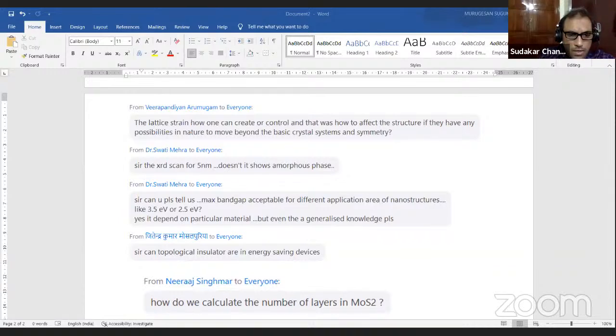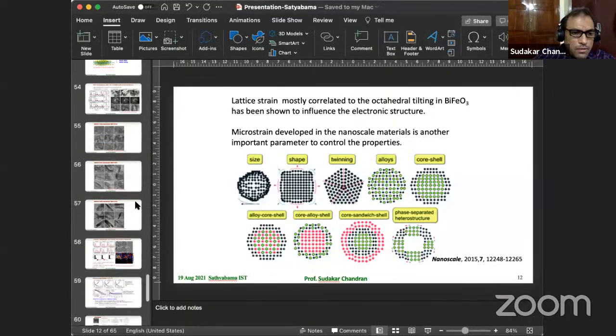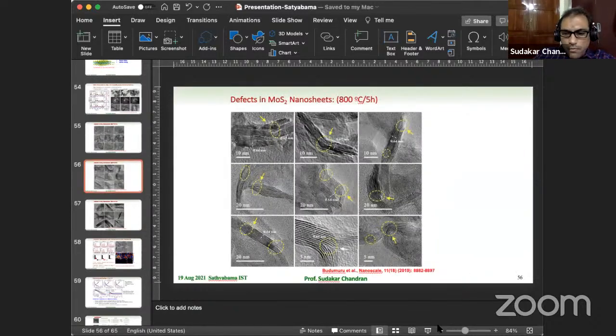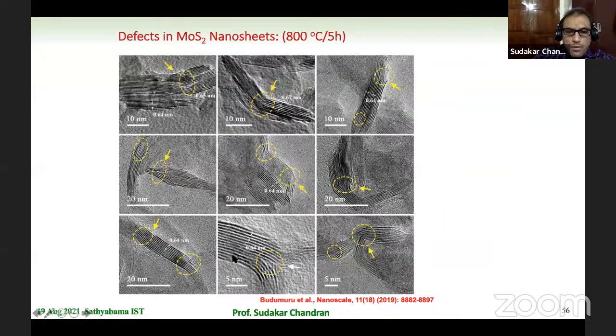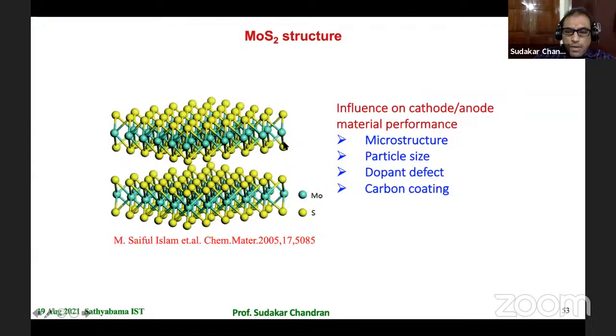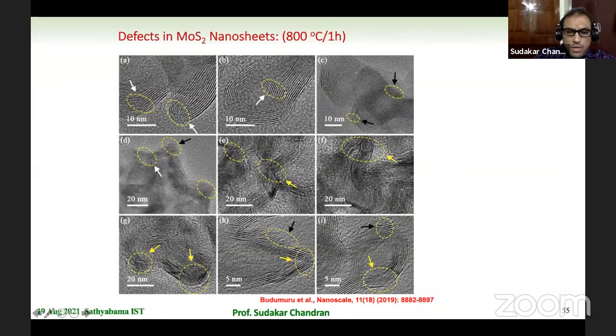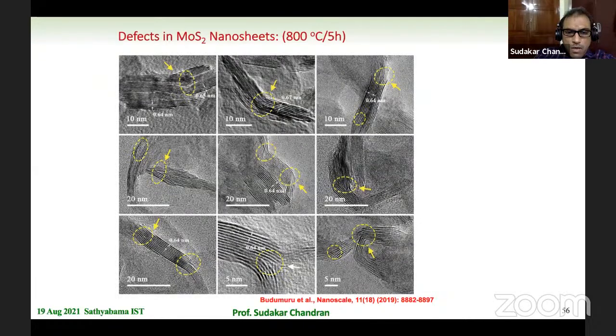So how do you calculate the number of layers in MoS2? In the high resolution TEM I showed, should I share this? Let me once again share this. Can you see the slides? For example, here you see this white to white is 0.64 nanometer, which is the distance between these two layers, 6.4 angstrom, and therefore you can count this. How many layers are there? 1, 2, 3, 4, 5, 6. Like that, you count it and you get the number of layers.